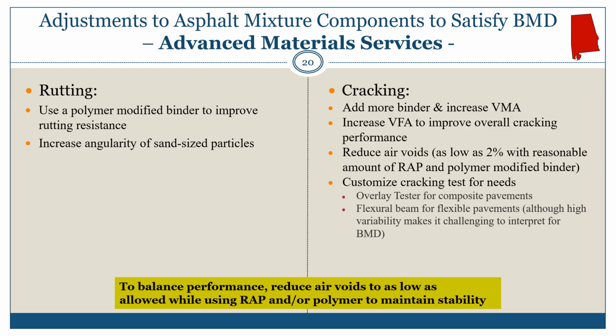If the state agency is going to have a rutting test and a cracking test, reducing the air voids and allowing more asphalt in can always be checked on the rutting tests. He also says he likes to customize his cracking tests for different needs. He likes to look at the overlay tester for composite pavements. He likes to look at the flexural beam fatigue for flexible pavements. And so he actually looks at different performance tests based on the mode of cracking he sees in the field.